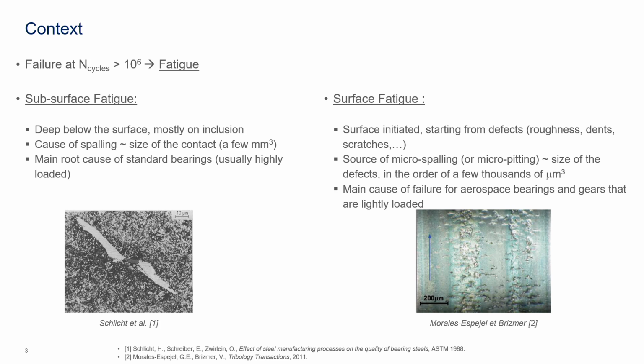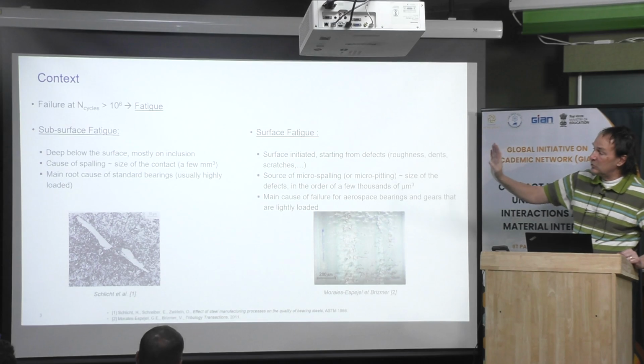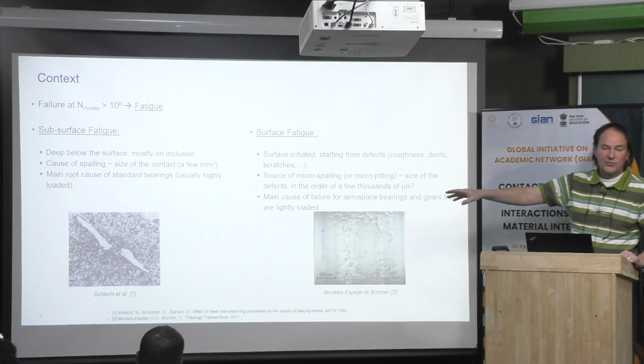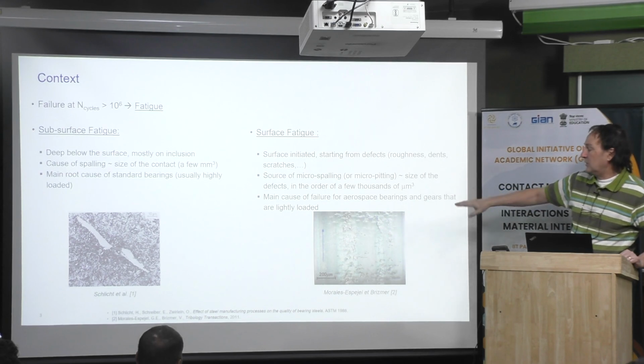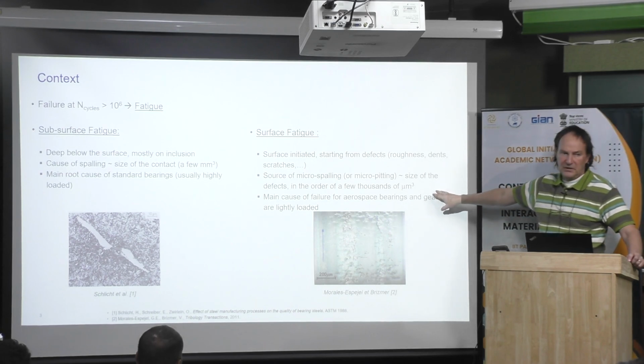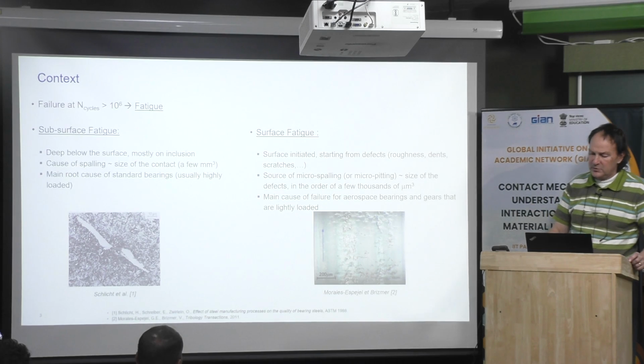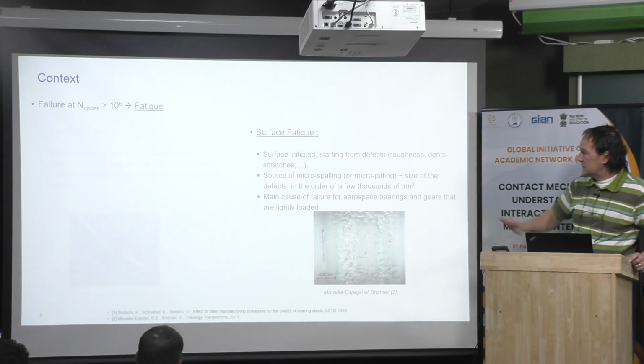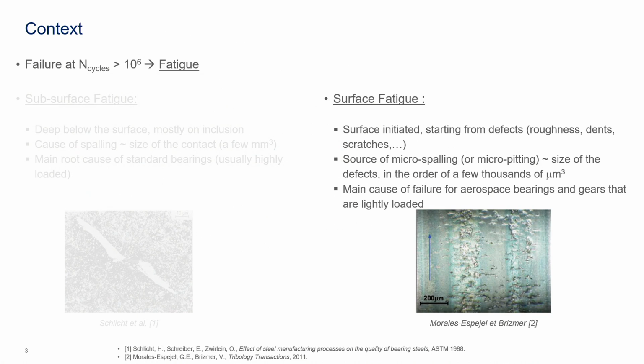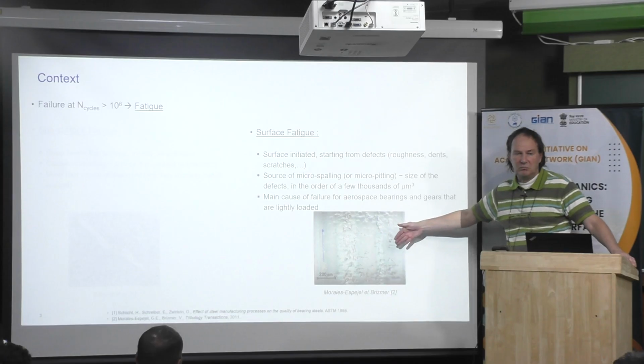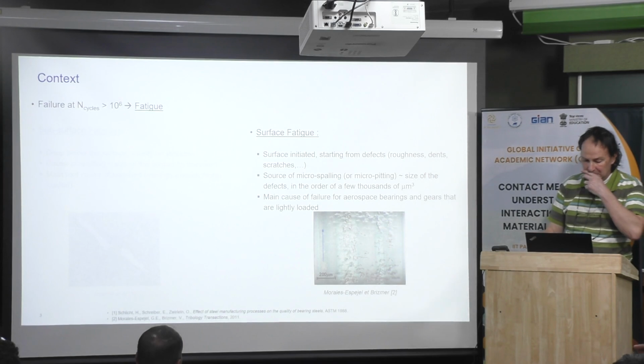And on the right, you can see a surface with many dents. Okay, this is completely different. In the old time, we used to have subsurface fatigue, or for bad quality materials, metal. But now we have mostly this type of damage, especially for aerospace application. And this is what we are looking for. The size is very small, and they are very shallow, no more than a few micrometers.